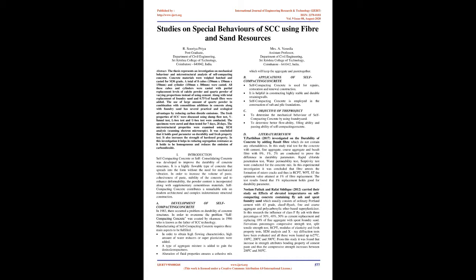The use of a large amount of quartz powder in combination with cementitious additions in concrete along with foundry sand has several practical and ecological advantages by reducing carbon dioxide emissions. The fresh properties of SCC were discussed using slump flow test, V-funnel test, L-box test, and U-box test. The specimens were cured and then tested for 7 days and 28 days. The microstructural properties were examined using SEM analysis, scanning electron microscopy.